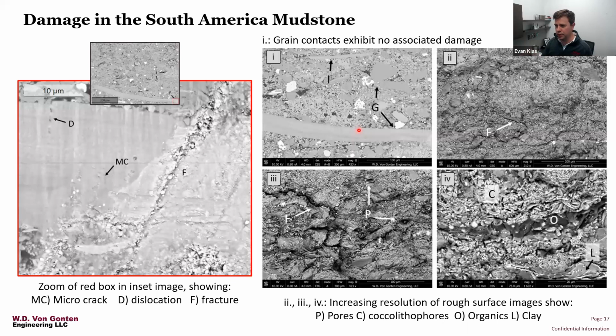In fact, when we talked a little bit before about 3-point bending at these grain contacts, we see very little of that here. You might expect to see these elongated grains exhibiting tensile fractures, but those didn't seem to be present. We don't have a lot of grain crushing at contacts.